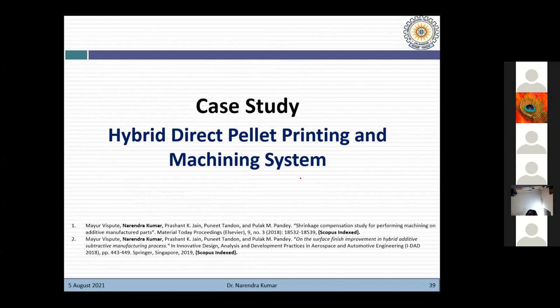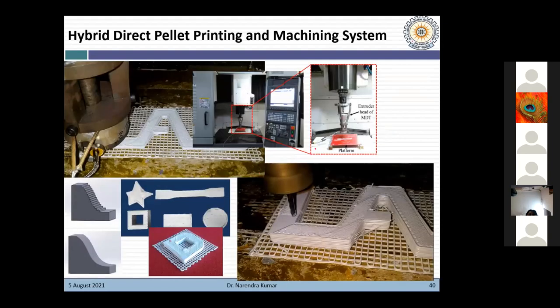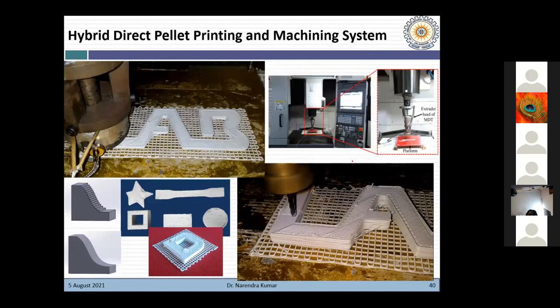Another case study which we have attempted is the hybrid direct pellet printing and machining system. Since we were using the CNC machining center for additive manufacturing purposes, we explored the same setup for machining also. So what we did in this area, we developed a hybrid direct pellet printing and machining system. First we performed additive manufacturing, then we machined the same part. You can see here we are fabricating a part using additive manufacturing, and here at the bottom you can see the machining tool is removing material from the top surface.